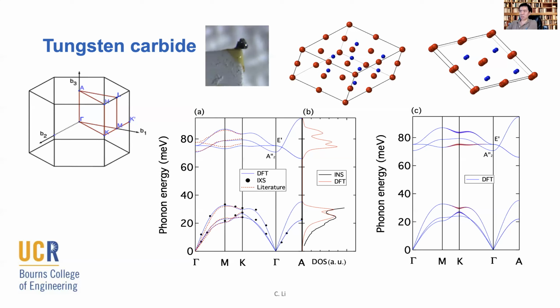So we thought, oh, this is great. We're going to look with inelastic scattering and try to figure out if we can actually see them. Honestly, I wasn't optimistic we were going to see anything, since when we do inelastic X-ray scattering, at least the non-resonant inelastic scattering related to phonons, we treat the photons as just a classical particle that's scattering off some potential wall. The scattering theory doesn't really take into account the polarization or any detailed interactions. But we tried it anyway to see if there's anything exciting we can find.